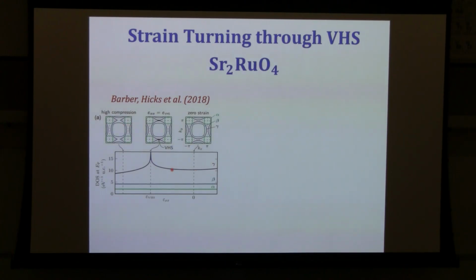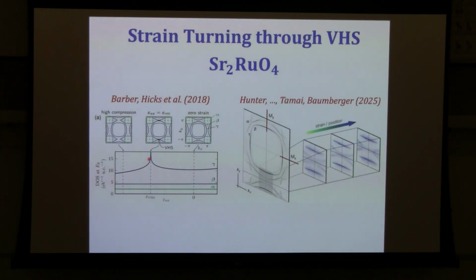So this is the calculated electronic structure in the system. And it turns out that this calculation captures correctly where the system would cross the Van Hove singularity. Recently there's been a beautiful photoemission experiment which images the band structure as a function of strain. And you can really see how this saddle point topological transition in the Fermi surface is occurring at the edge of the Brillouin zone. So this allows you to measure what strain corresponds to the Van Hove singularity in the system.